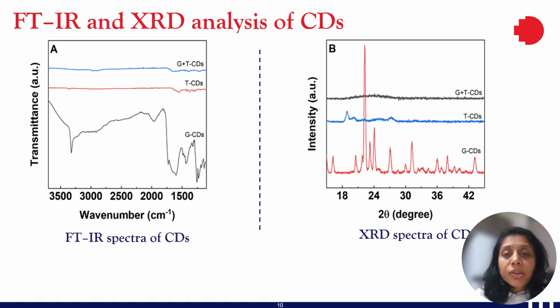And to understand the structure, X-ray diffraction patterns of the carbon dots were collected, and glutamic acid carbon dots exhibited an intense crystalline peak, which again supports that glutamic acid didn't chemically transform into carbon dots. The sharp multiple intense peaks suggest the ordered crystalline structure, which leads to fewer defect sites and lower fluorescence. In the case of tryptophan carbon dots, they displayed broad and low intensity peaks, which is typical of amorphous carbon. The bulky indole ring disrupts the graphitic stacking, leading to a more disordered structure, enhancing the photoluminescence.